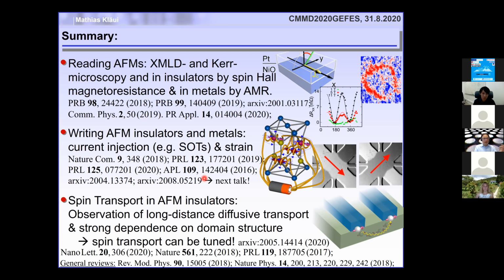So I think there are a lot of groups working on these antiferromagnets, but we've been working on manganese platinum and iridium manganese, and you have to get the composition pretty correct in order to get a good collinear antiferromagnet. And then the XMLD signal is very small, so they're also tough to image. So very exciting. It's just an experimental problem.